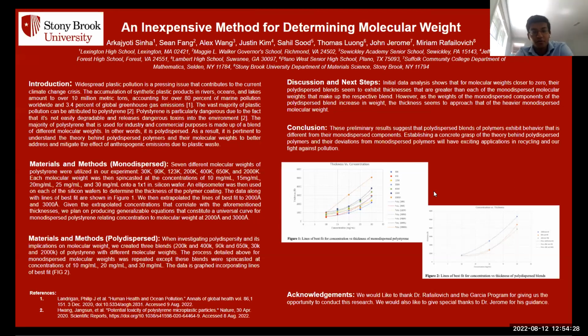Initially comparing the monodispersed and polydispersed data tells us that at low molecular weights, the polydispersed blends exhibit thicknesses that are greater than each individual monodispersed component. However, at high molecular weights, the polydispersed blends seem to approach the thickness of the higher molecular weight monodispersed component.